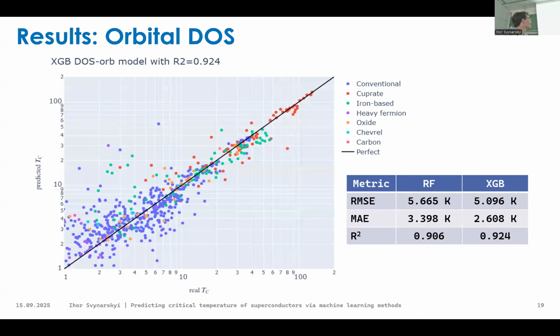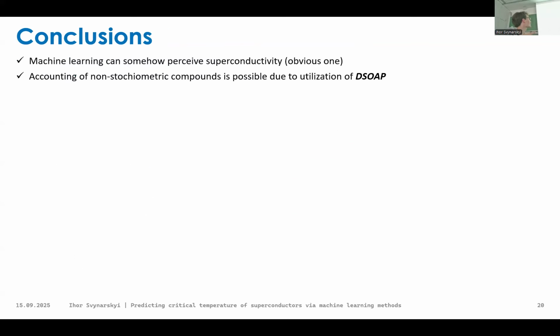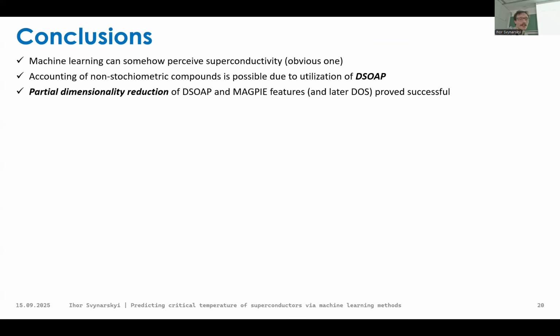Yeah. And conclusions are three, as follows. We could perceive superconductivity somehow, because as you can see, it tries to place the dots on this line. And the second conclusion is accounting of non-stoichiometric compounds is possible if we are using this disordered SOAP. So it's an improvement. Partial PCA is good for reducing the number of these features because they are quite sparse, having a lot of zeros in this matrix.